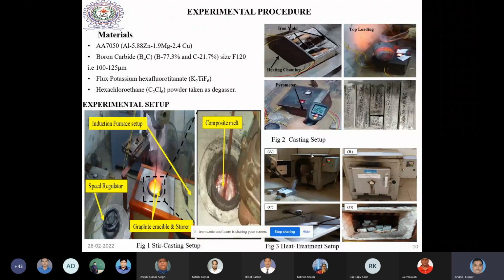So amalgamating everything together, this is the iron mold I have used. This is the stir casting setup that was there at NIT Agartala. Then I have tried from 700 to 800 degrees centigrade. We should not pour it directly at room temperature, so a heating chamber was developed so that the mold temperature was fixed at 450 to 500, or more precisely 400 to 450 degrees centigrade. Then we poured it, and we went for slow cooling to reduce the shrinkage allowance.